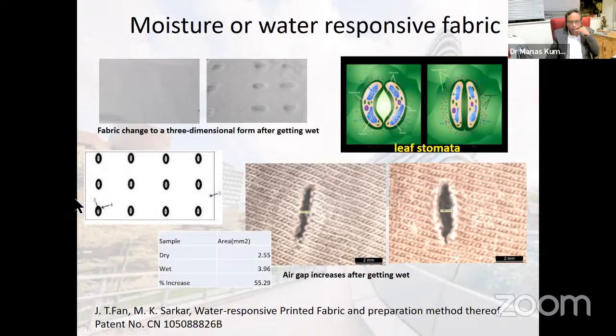And then we printed it using the printer, in such a way that the outer portions are this hydrogel and the inner portion is nothing, it's only the fabric. So when we measured these portions, we saw a nice achievement. So this is the dry fabric and this is the wet fabric. You can see the air gap, which is here. Area is 2.55. Now this area has almost doubled, 3.96, around 55.29% increase in the air gap. So that gives you much more benefit in terms of air permeability. We filed a patent on that, but we are still working on this area, and I can't disclose many things at this stage.